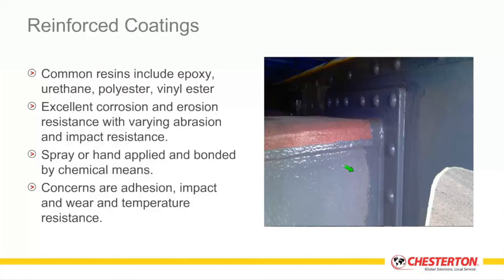Here you can see an application on a vibrating screen application, and a high ceramic loading system is being used in the transverse structural members, and on the areas where it's exposed to more corrosive flow, a thinner film coating system has been used for more corrosion resistance, whereas a highly ceramic reinforced system is used for wear and abrasion resistance.